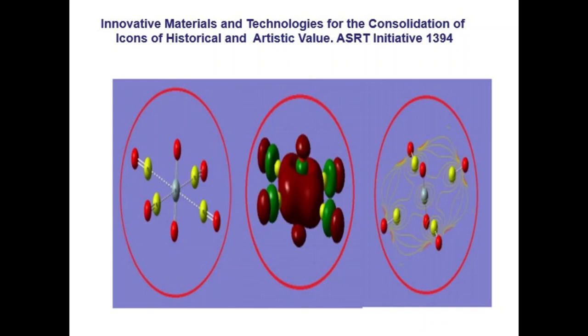We produced two metal oxides — a bi-metallic nanomaterial — both in nanoscale, as a colloid and as a powder, as shown. We performed UV-visible analysis to confirm the material's effectiveness against light, and used electron microscopy to examine the surface structure of the bi-metallic nanomaterial. We then applied it as a protective layer. This work was submitted as a patent.